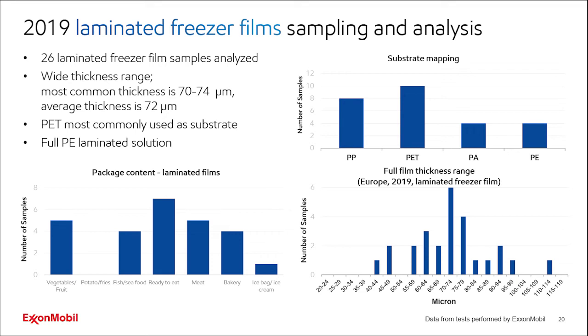Again, the vertical axis is the number of samples, and on the horizontal axis you have the different types of substrates: PP, PET, PA, and PE. Again, a very wide range of film thickness. Here we are talking about the total film thickness, so the thickness of the substrate plus the adhesive plus the PE layer, right? But the most common thickness is in the range of 70 to 74 micron, and the average is 72. Then PET is the most common substrate as well.